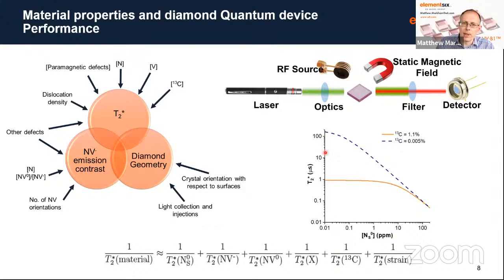This plot is basically spin lifetime versus the nitrogen content, and the assumption is that no other parameters are affecting the spin lifetime. So this is what you'd expect for the spin lifetime, depending on whether it's natural abundance material or carbon-13 depleted material.